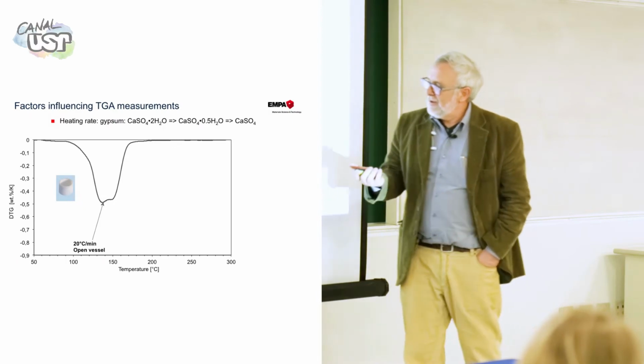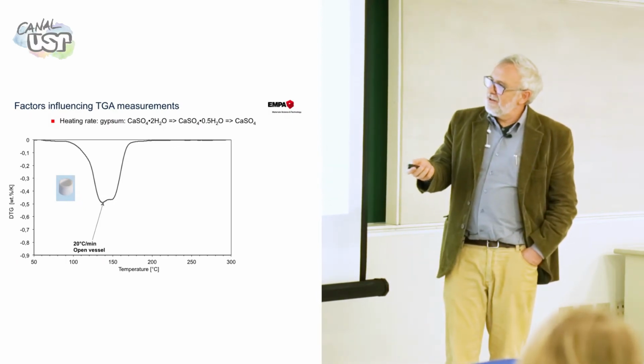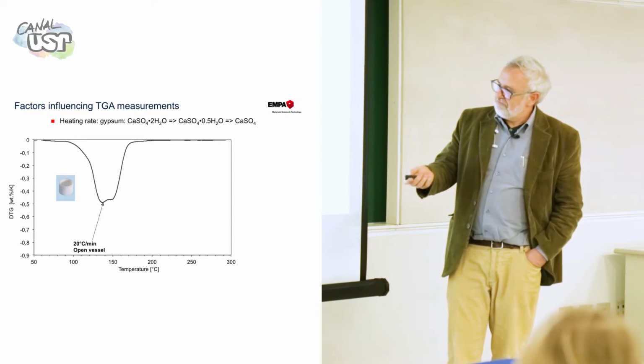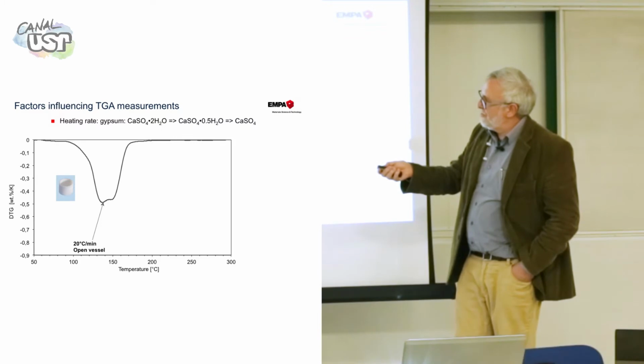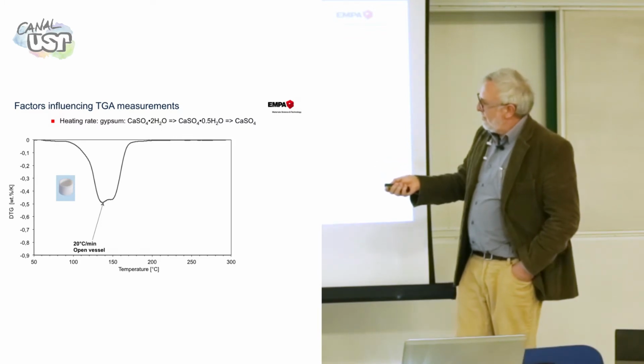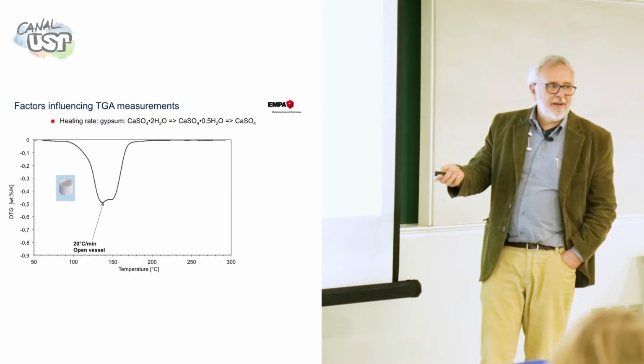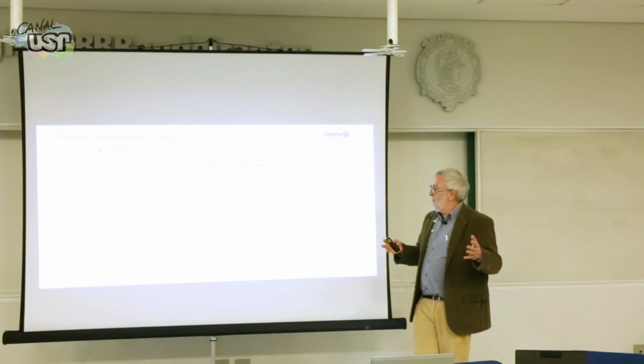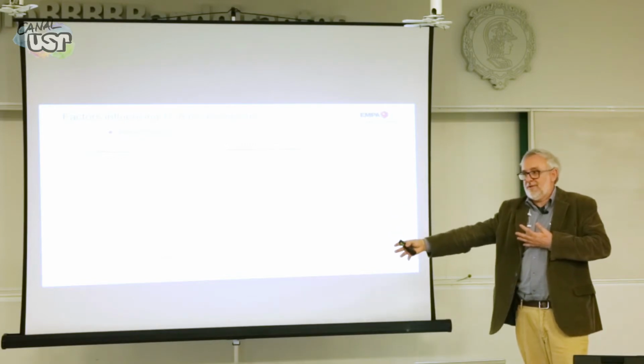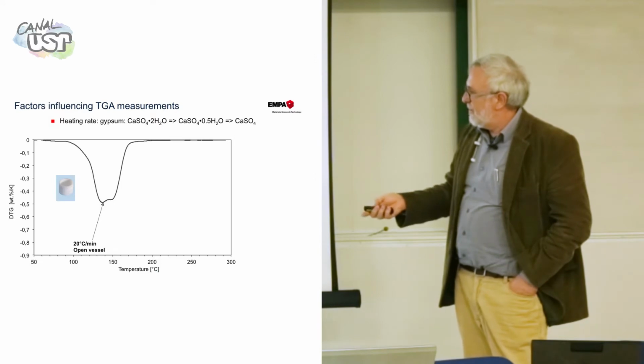Gypsum is really interesting because what you have here is the derivative. Below 100 degrees centigrade it starts to lose water in one peak, and then this is two peaks overlapped. Because at 140 degrees or something, 130, you first lose 1.5 molecules of water, then you lose the remaining half molecule of water. This is hemihydrate, and here it goes to anhydrite. But the peaks overlap, and this is 20 degrees per minute.